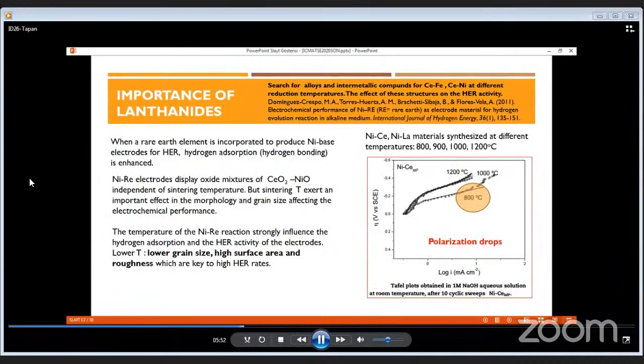In another work on lanthanides synthesized at different temperatures, it showed that nickel rare earth materials synthesized at low temperatures also offer higher hydrogen evolution rates. The electrochemical performance of nickel rare earth electrodes demonstrates that true catalytic activity is observed when rare earth elements are incorporated to produce nickel-based electrodes for hydrogen evolution. Based on this overview, since hydrogen evolution reaction mainly involves surface processes and is affected by the surface composition of the catalyst, the type of metal alloy is a very important factor for the electrode reactions. This information may explain the paradigm of our catalyst in this study.